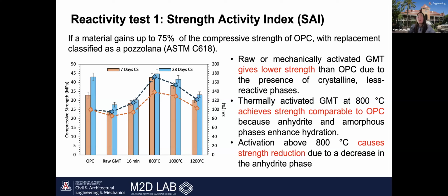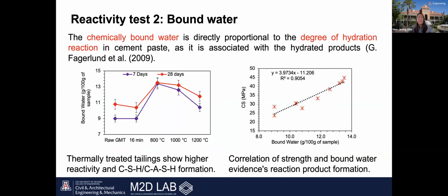And at higher temperatures, such as 1,000 Celsius degree and 1,200 Celsius degree, the strength starts to decrease again. This drop is related to the loss of anhydrite and changes in phase composition. So overall, the thermally activated GMT at 800 Celsius shows the best performance, achieving more than 100% SAI.